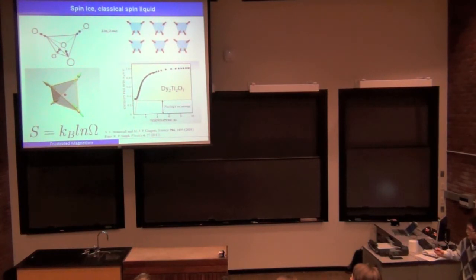And this puts spin ice material as a classical spin liquid, in the sense that it has this huge ground state degeneracy, but because of the large spin, the dynamics of this material at low temperature is not controlled by quantum mechanics, but instead by thermal fluctuation.